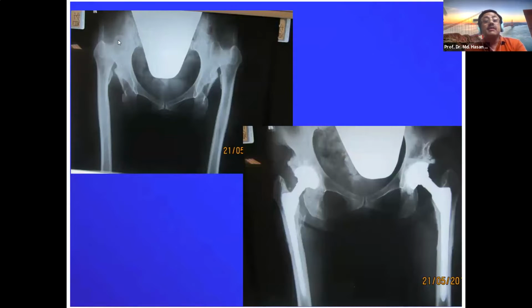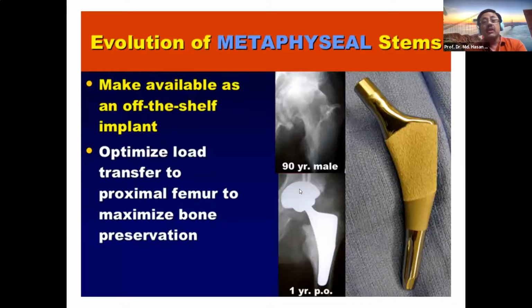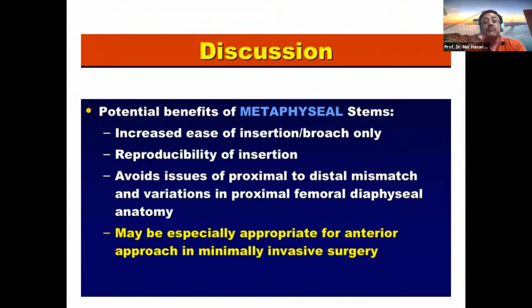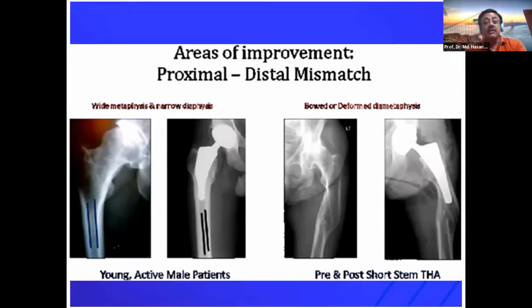And now see, here is a bilateral dysplastic hip. The center of rotation of the head is even higher in both these hips. And what will you do? In this case also, you have to use the S-ROM. So there is also evolution of metaphyseal stems, made available as an off-the-shelf implant, optimizing load transfer to the proximal femur to maximize bone preservation. There are some benefits of metaphyseal stems, and see this case, a young active male patient with a narrow diaphyseal canal, a narrow medullary canal, and in this case you may use this short metaphyseal stem. And another case where there was a subtrochanteric fracture with angulation and a united fracture, and in that case also you can use the short metaphyseal stem.